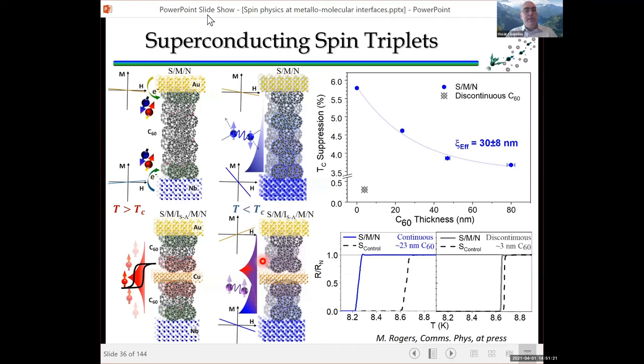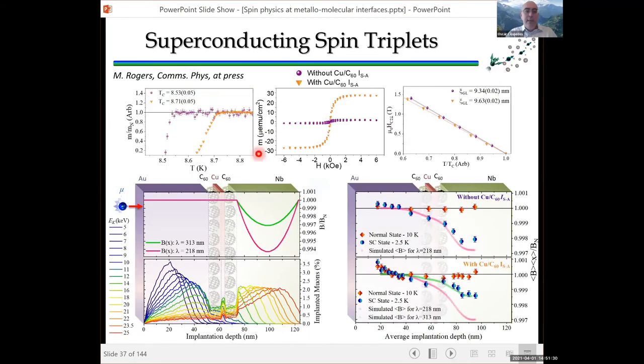So what we see is that if we compare, again by doing low energy muon spin spectroscopy, the two structures, if we have plain niobium, so superconductor, with C60, we can measure the Meissner effect, the diamagnetic reduction of the local magnetic field. What you see at the bottom in this graph is the change in the local magnetic field, which is being reduced from 1 to 0.997 due to the Meissner effect. Sorry, the computer is going very slowly.